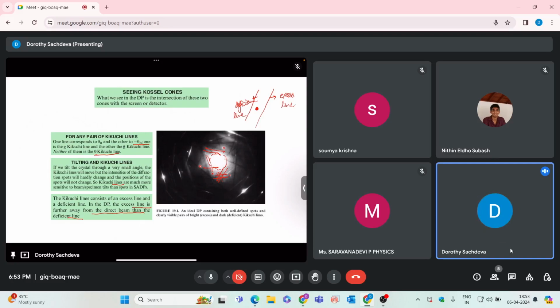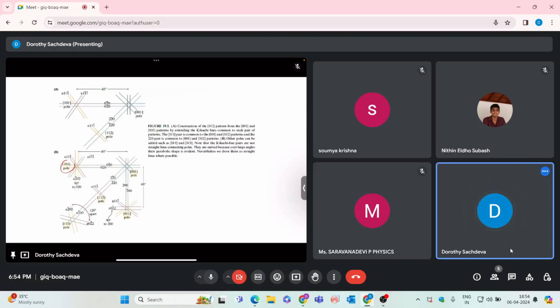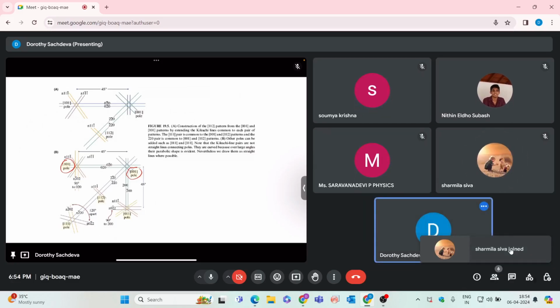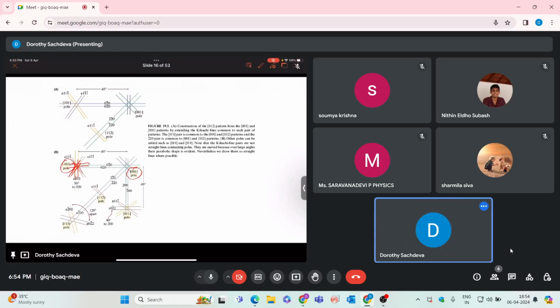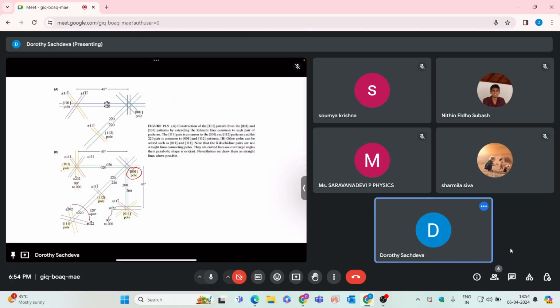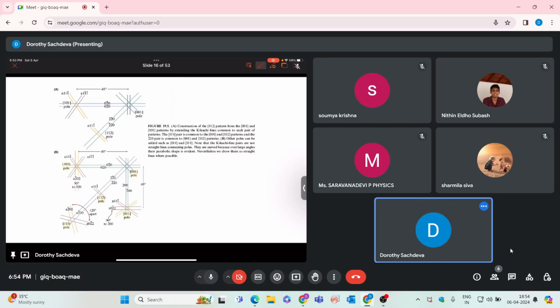So if you want to go from the 101 zone axis to the 001 zone axis, then you can see that you will have three lines which are interacting. Suppose these are the lines, sorry, there are four: this one, this one, this one, and this one. So the line which corresponds to the 020 plane, you need to follow that line. Only that line will take you to the next zone axis, which is 001.